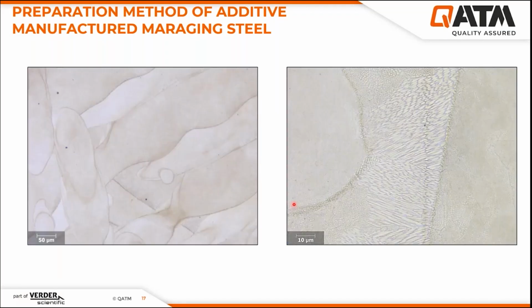When we go to the optical microscope, we can see the laser layers under the microscope and also the grain boundaries and also the boundary between the laser layers. Here, to have very clear boundaries, it is very important not to have deformation and to have the right metallographic preparation. Because of that, metallographic preparation with the right material, consumables, and also right parameters is very important.